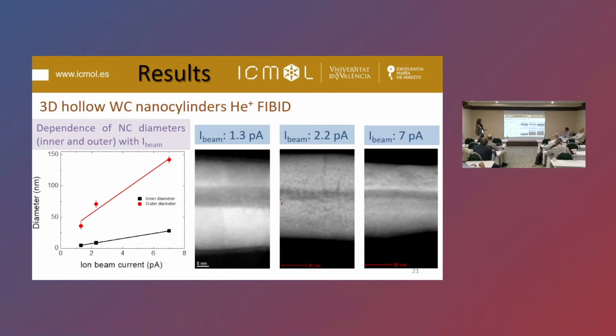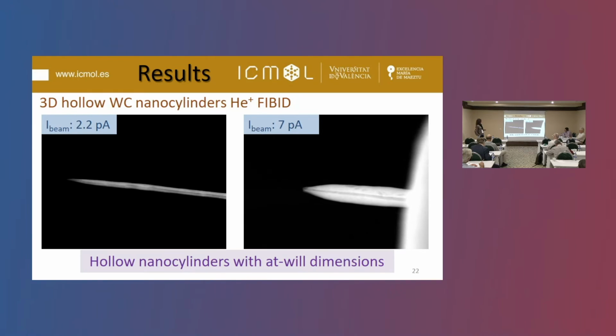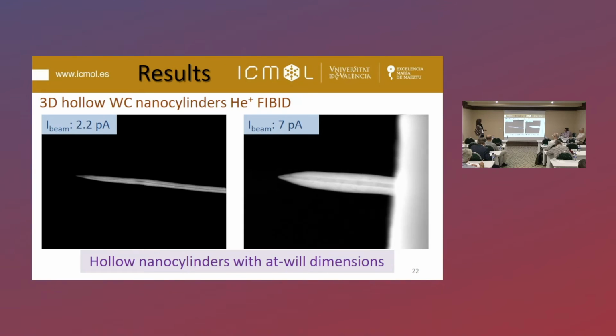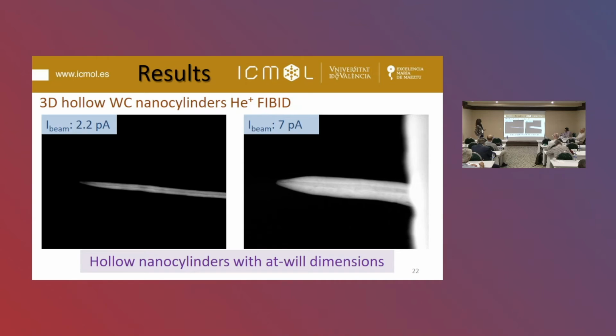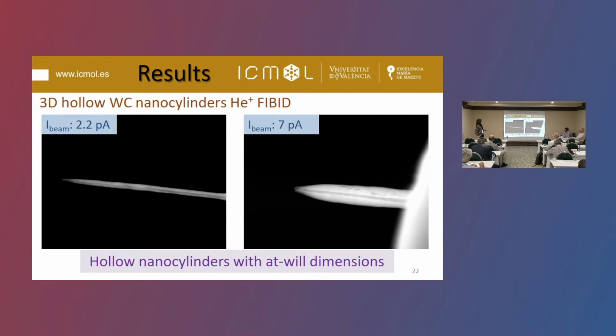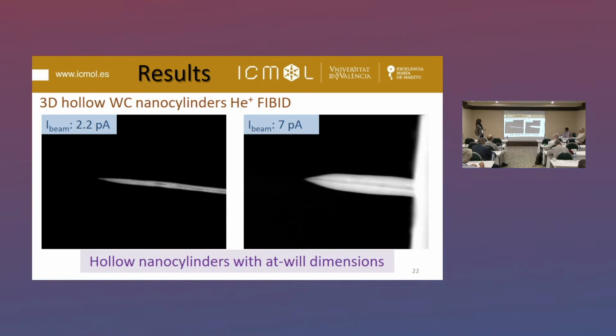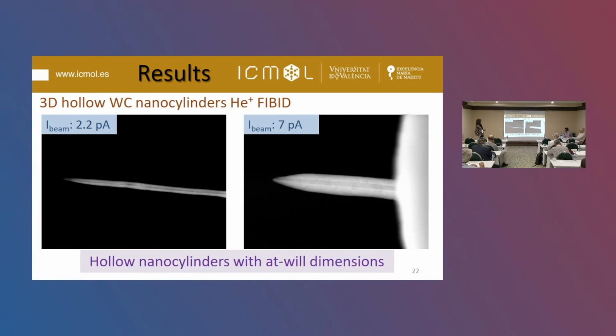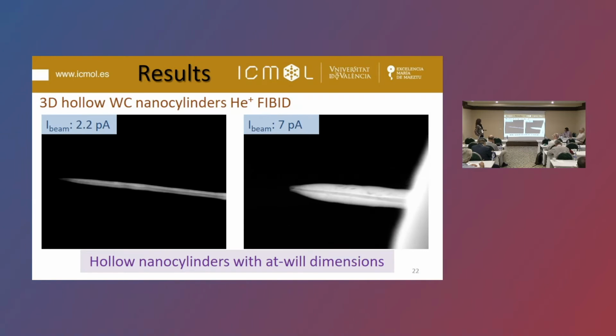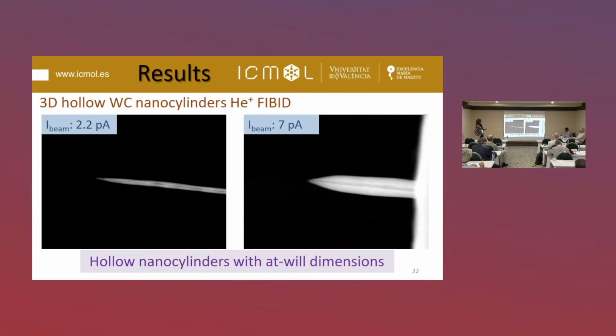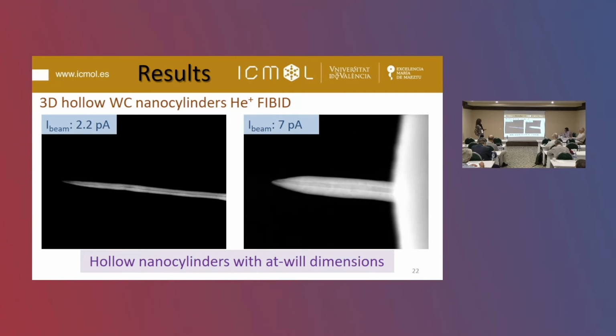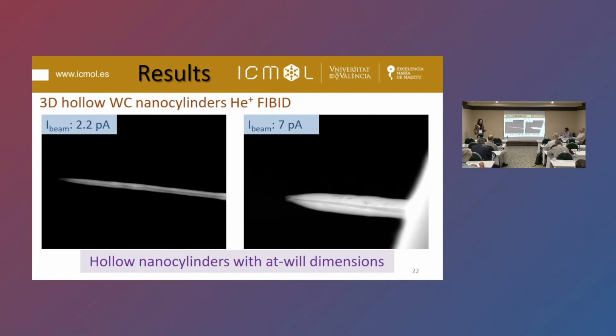The ion beam current correlates with the ion beam spot, so we can just increase the size of the outer and inner diameters by increasing the ion beam current. In that way, we can control the 3D dimensions of these hollow nanowires. Interestingly, you can see in this 3D tomographic reconstruction how the cavity, the hole in these nanocylinders, starts from the top part and finishes at the bottom part. With that, we demonstrate that we are able to create these hollow nanocylinders with at-will dimensions, like hollow nanowires.